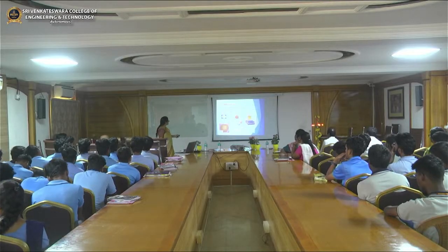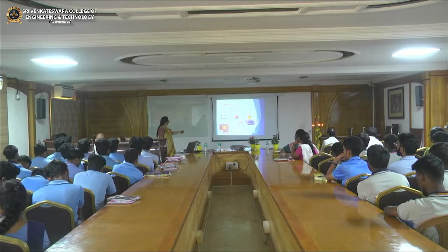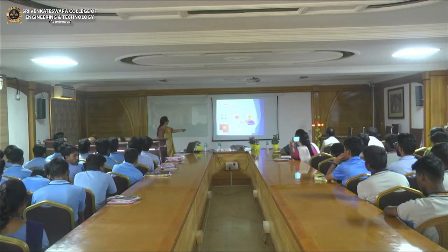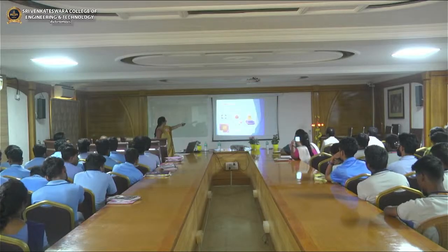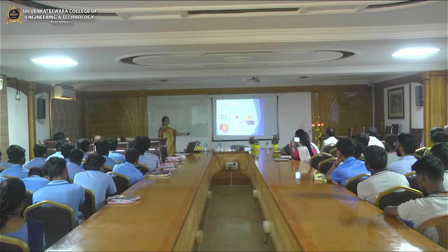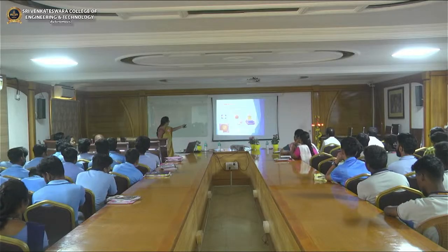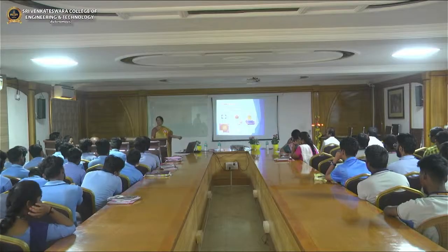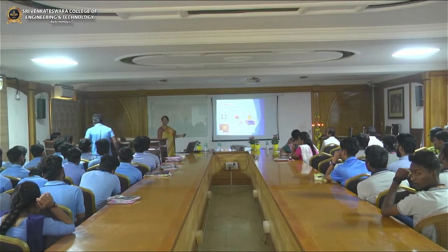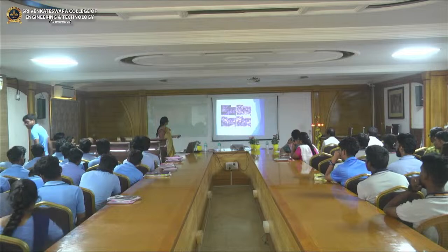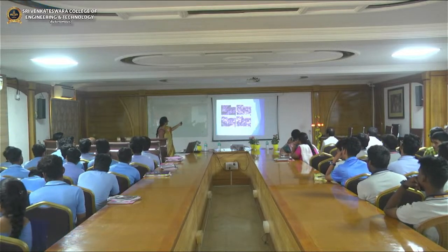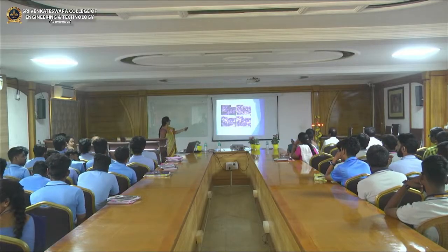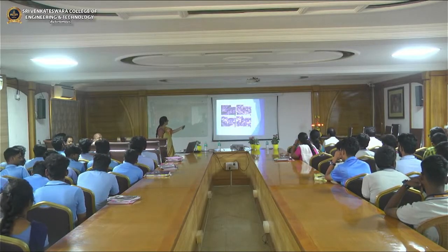This is the process to be followed in getting the particular solution. We have to mix it and heat the material on a magnetic stirrer, and finally we do filtration and get the yellow cadmium sulfide powder. Here, this is pure cadmium sulfide without any capping agent. The next ones are PEG cap, EDTA cap, and PVP cap.